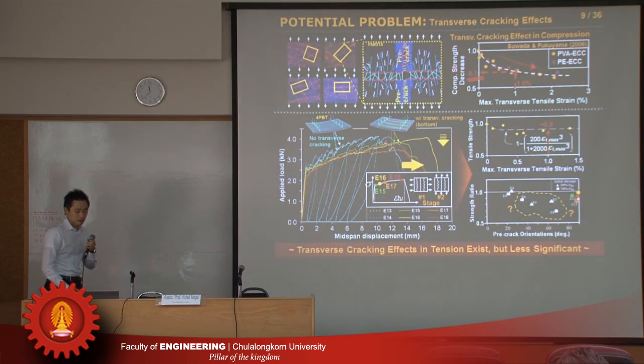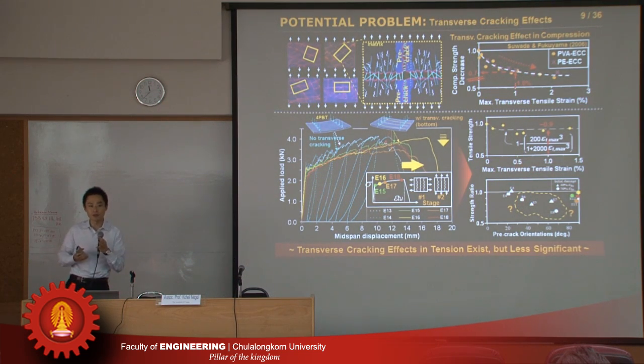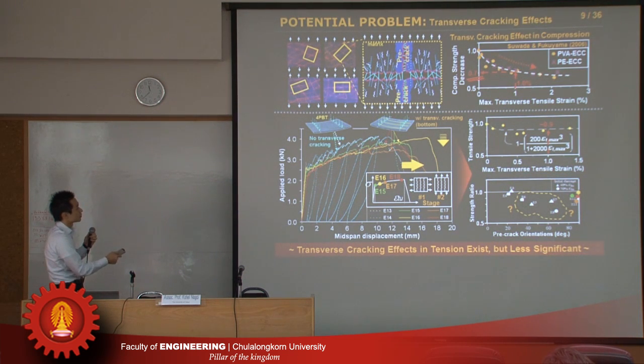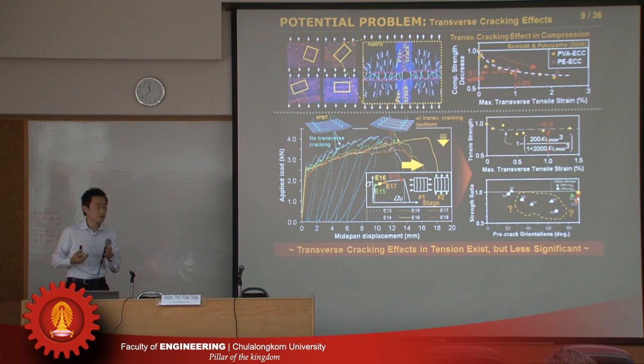So that was the case of 20, 45, 70 degrees. And in the case of 19 degrees, we don't have any shear sliding because the initial crack is perpendicular to the secondary principal loading direction. But we still have a reduction of the strength, a little bit, 10%. Probably it is because of the initial crack. In the vicinity of the crack, the fiber does not work well. That causes about 10% reduction in the strength. Anyway, we did the test to check how it reduces.